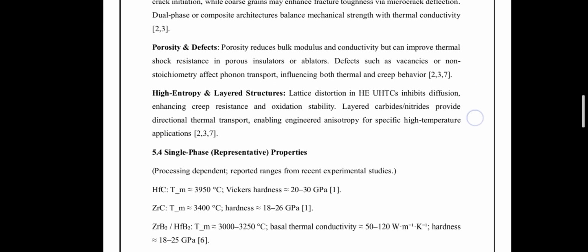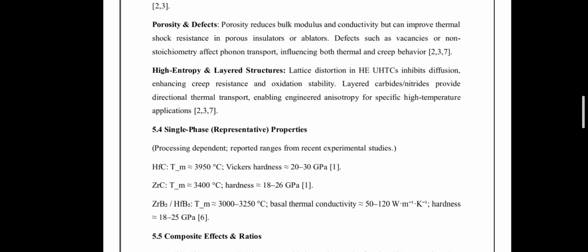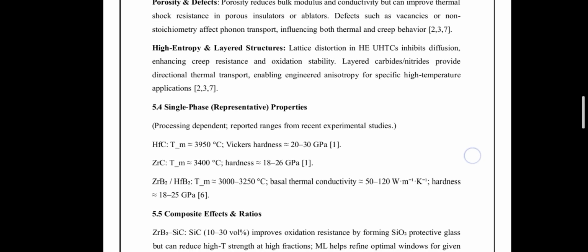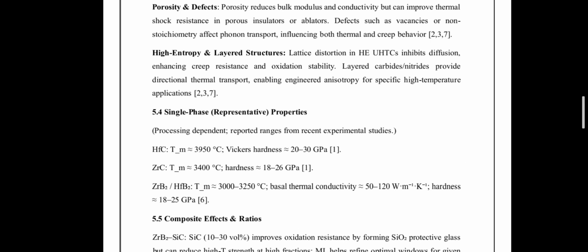Next are the high entropy and the layered structures. In high entropy ultra high temperature ceramics, lattice distortion inhibits diffusion and improves the creep resistance and oxidation stability. Layered carbides and nitrides enable directional thermal transport, allowing engineered anisotropy for target high temperature applications. Next are their representative single phase properties, which are processing dependent.